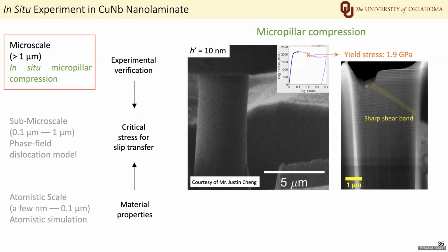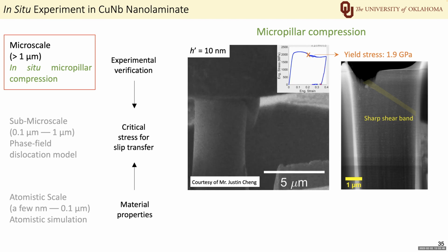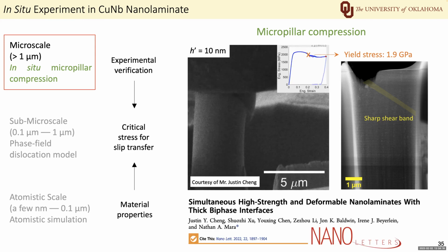In the meantime, my colleague at the University of Minnesota conducted an in situ micropillar compression experiment. They found that when the copper niobium laminate containing 3D interfaces yields, a sharp shear band is formed, and the yield stress is 1.9 gigapascal, which is close to the prediction of the phase field dislocation model. So based on both the computational and experimental results, our joint paper was published in Nano Letters last year.